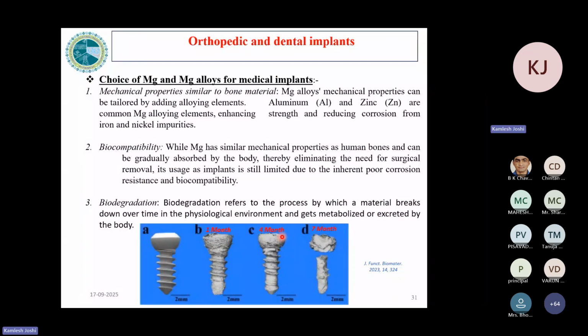So what are the main properties due to which they have become a competitive material for titanium and stainless steel? First thing is that their mechanical properties are similar to the bone material. And then these properties can again be tailored using alloying elements like aluminum, zinc, and so on. These alloying elements will enhance the strength and reduce the corrosion forming impurities like iron and nickel.